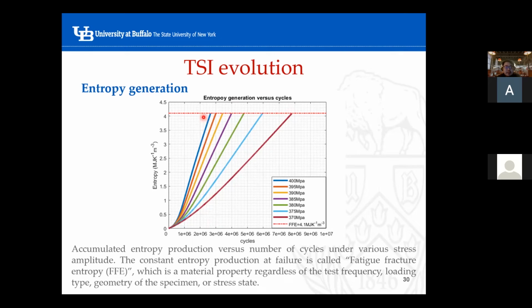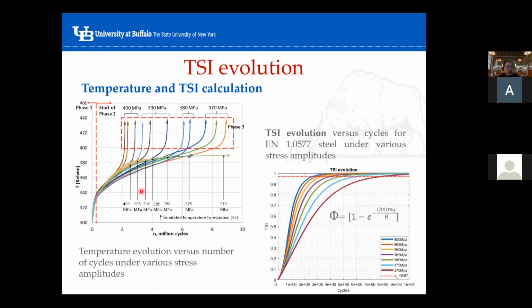This entropy is called the fatigue fracture entropy, and the fatigue fracture entropy depends on the material, not the geometry, not the test frequency, or the loading type — it is related to material. So the fatigue fracture entropy for this material is around 4.1.